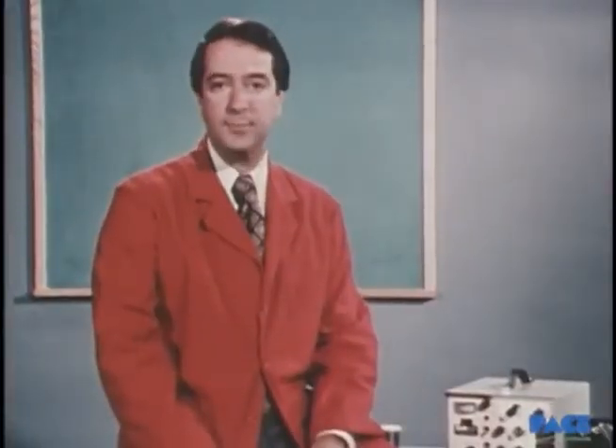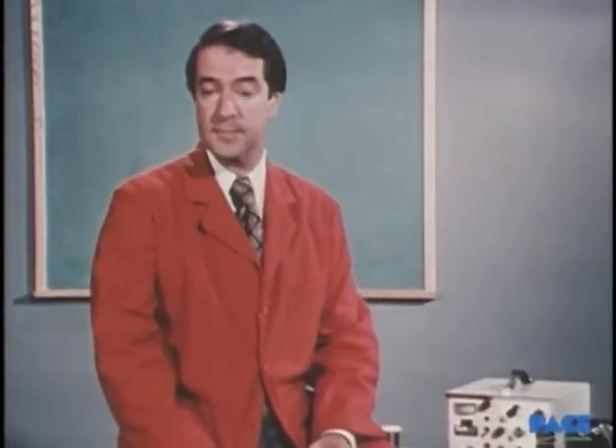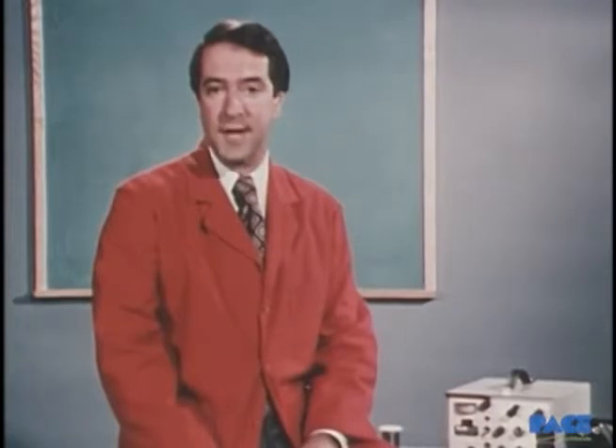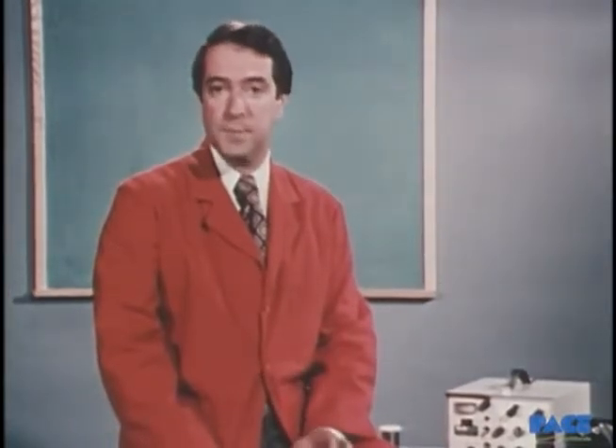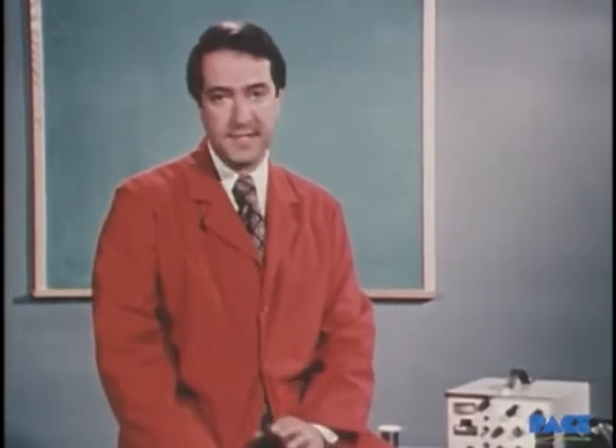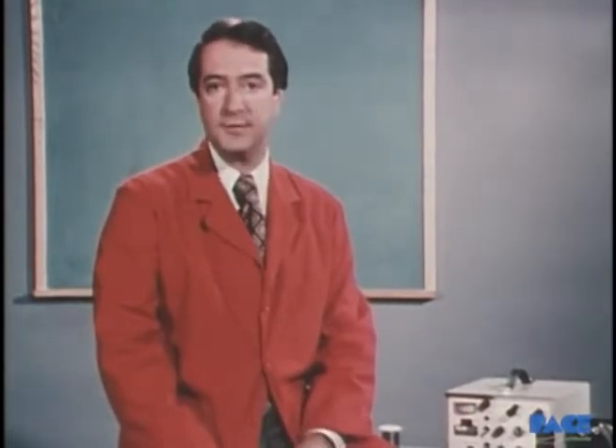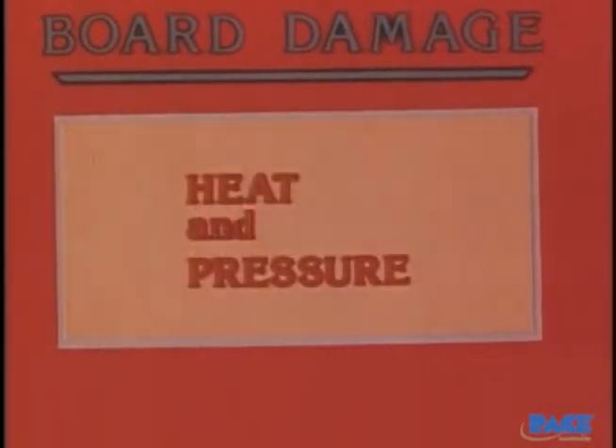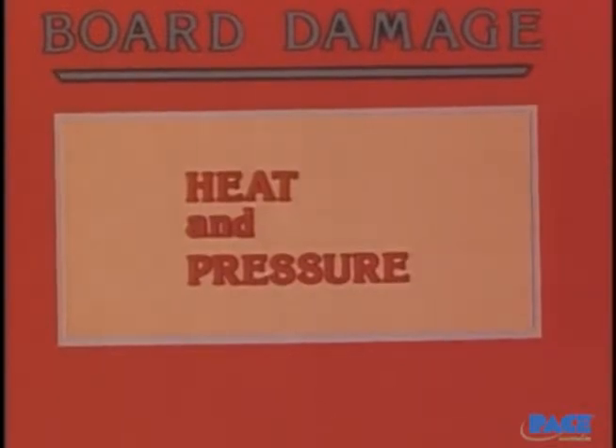Heat rate recognition, then, is our workpiece indicator for high reliability soldering. It makes a complicated problem of control very simple. Just watch and see how long it takes the solder to melt at the joint. It should melt within 2 seconds. If it takes any longer than that, you're increasing your chances of damaging the board. Board damage comes mainly from heat. But it's not only the heat that does it. It's heat combined with pressure.